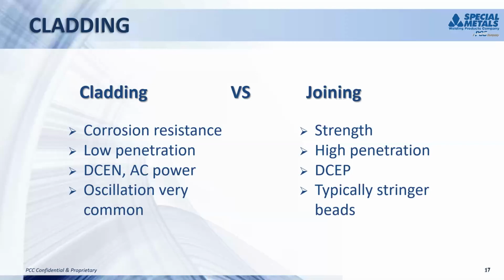And then as we talk about the difference in what we're doing when we're cladding a piece of equipment or a component versus trying to join a component. The reason we're cladding this is primarily for corrosion resistance. We're not really adding strength to it. We want to use a less expensive steel to make the structural component, and then we want to clad a layer of nickel alloys to protect that steel from the rest of the environment. So we're worried more about corrosion resistance and matching, whereas when we're joining, we're really worried about matching the strength, so that weld has just as much strength as the rest of the component.